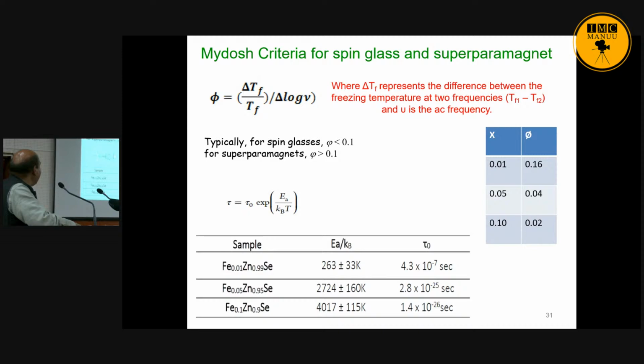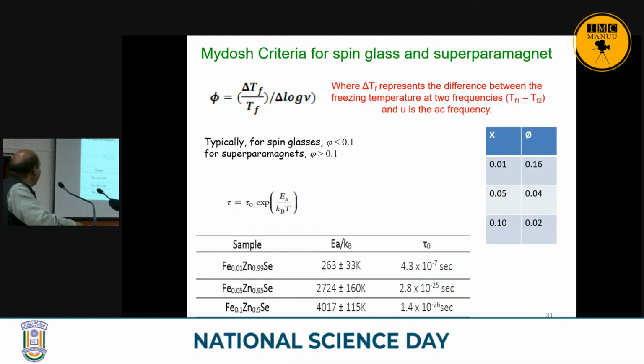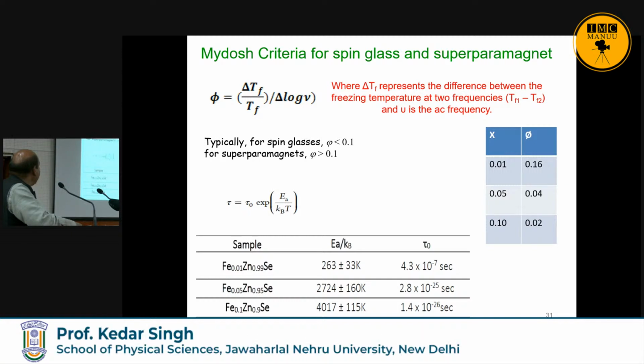If this is for spin glass, then the Mydosh parameter will be less than 0.1. If this is a superparamagnetic material, the Mydosh criterion will be greater than 0.1. Then you can see here the iron concentration 1%, 5 and 10. For 1%, it is showing a superparamagnetic material, but for 5 and 10%, it is showing spin glass behavior. So this is the finding. Then the same thing is supported here.